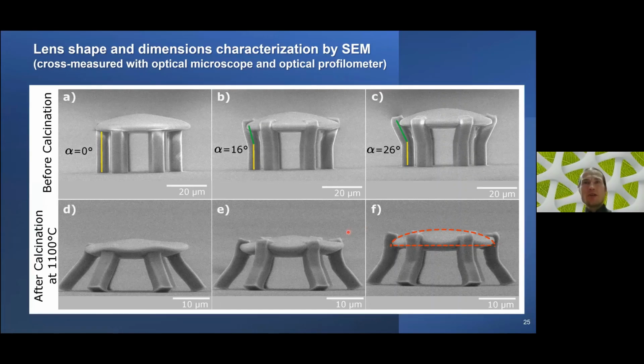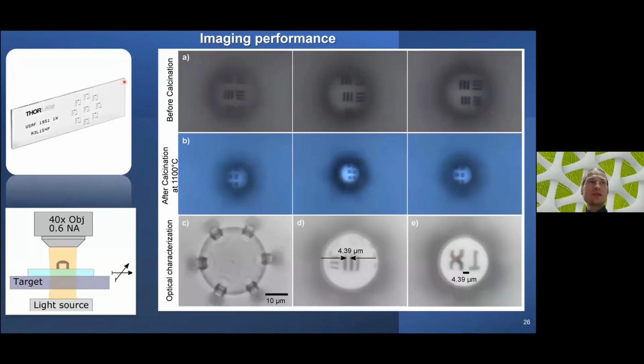And so how it looks in reality: the lenses on 0 angled legs, on 16, on 26. So 26 or around 27 seems to be the most convenient with the applied protocol, resulting in a non-deformed microlens which can then be put into action. And it was done using Thorlabs' USAF 1951 target structure, quite a standard one for the same comparison reason.